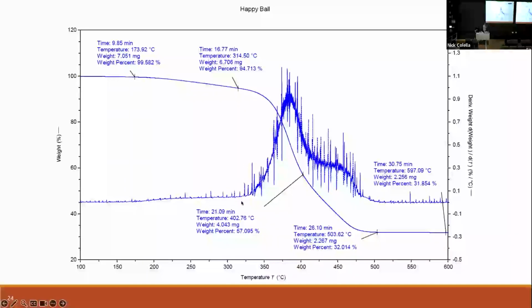So we see around 325, we really start to get a lot of degradation. Then we see kind of 2 decomposition steps. So that also gives us a hint about the chemical functionality that's inside the polymer. So we might have some material that can be burned off very easily, and then there's some other material that's left over that burns off more slowly and doesn't really burn off till we're above 400 degrees.